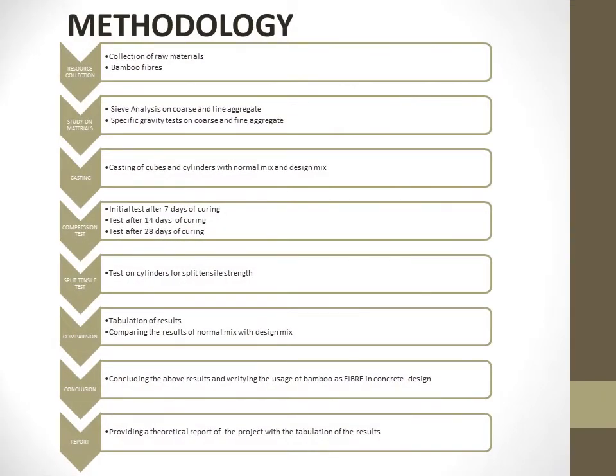This is our methodology for doing this experimental study. We had first collected the resources, and then we had studied the materials. We had casted cubes and cylinders with nominal mix and the fiber mixed concrete, and then we put those specimens for compression strength test and split tensile strength test, and then we compared the results of nominal mixed concrete and fiber mixed concrete, and then we came to a conclusion and we had done the report.